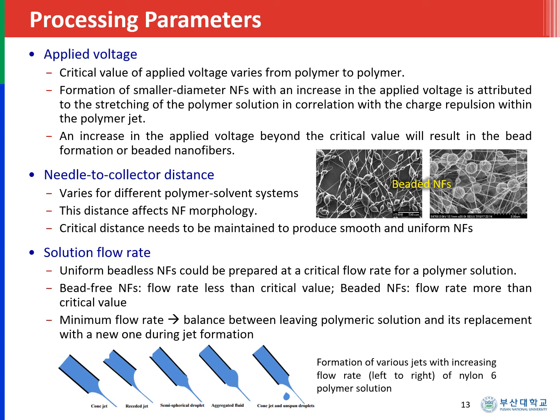There is a critical value of applied voltage for a particular polymer to be electrospun into nanofibers. There is no single applied voltage that could electrospin a plethora of polymers into quality nanofibers. The formation of smaller diameter nanofibers is possible due to the increase of the applied voltage, because this increase in applied voltage will cause stretching of the polymer solution in correlation with the charge repulsion within the polymer jet.